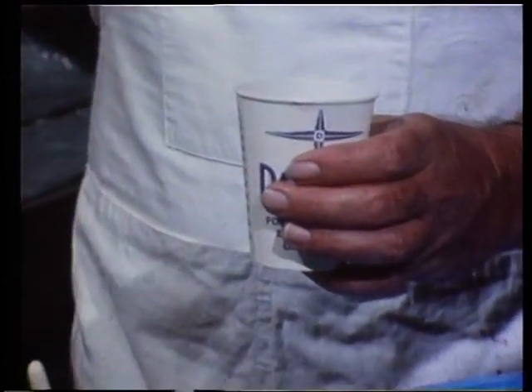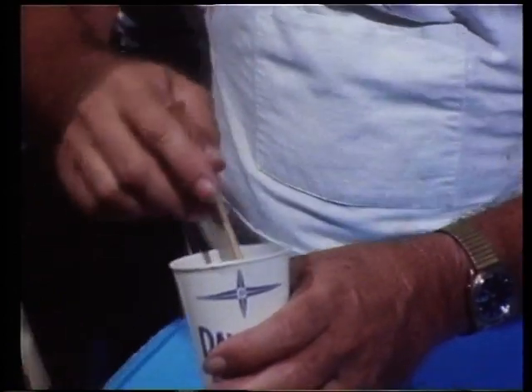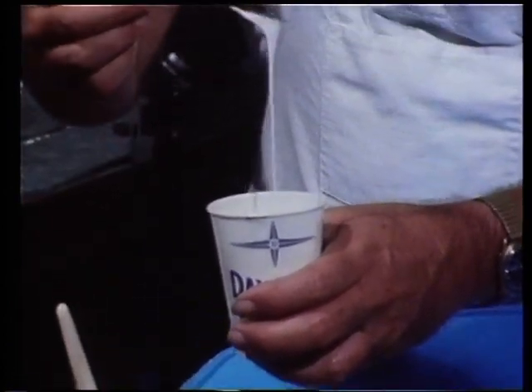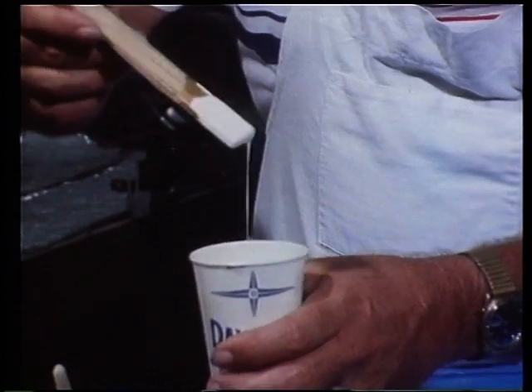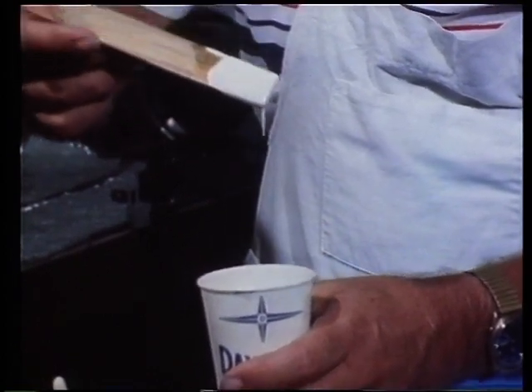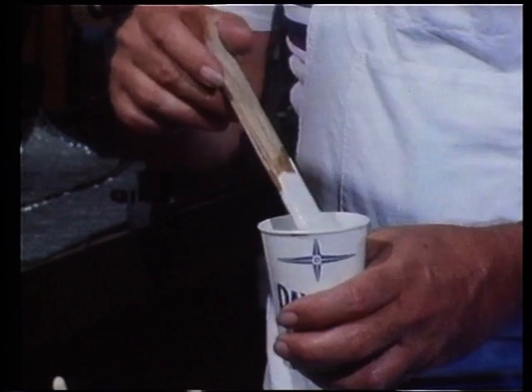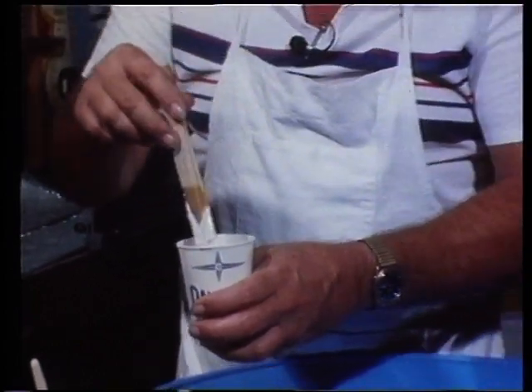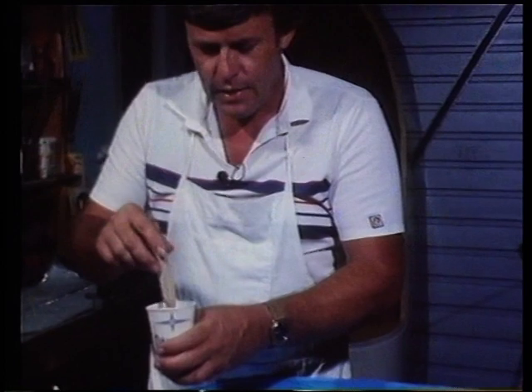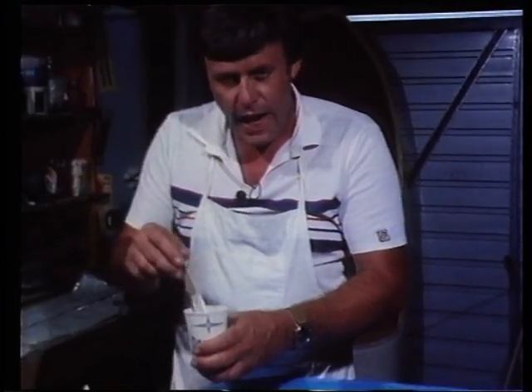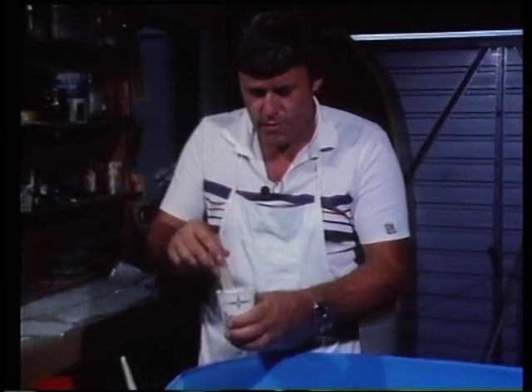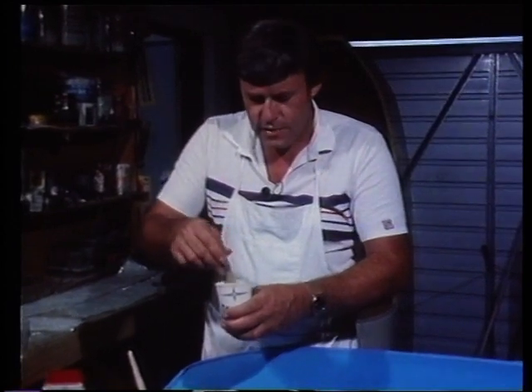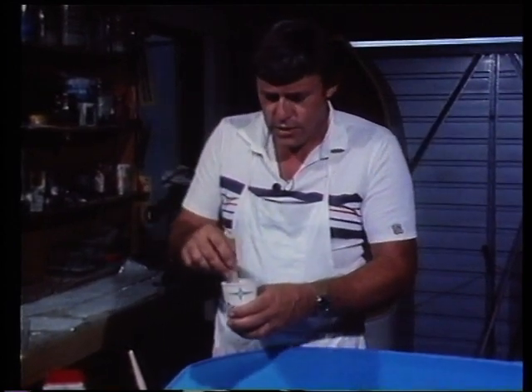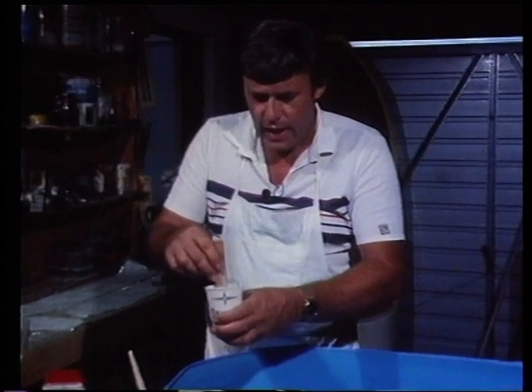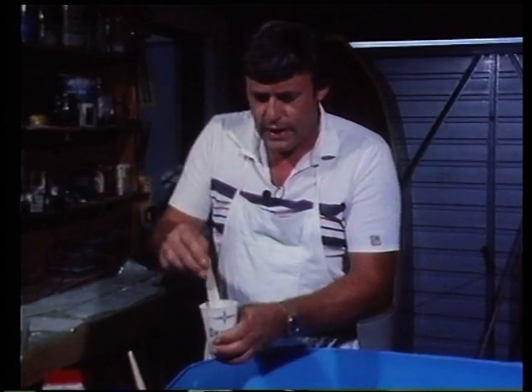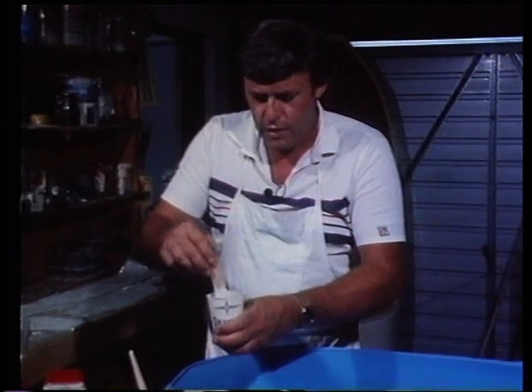Now gel coat has some interesting properties. If I just lift it on the stick there, you'll notice that it pours, but with still quite a large volume on the stick, it stops pouring. Now that means that it has a property called thixotropy. That's a great word, but it means the ability of a liquid to hang up on a vertical surface regardless of its viscosity, and you'll see in just a moment why gel coat has to be thixotropic. Now that means that stirring it, just agitating it like that, is not enough to distribute that catalyst evenly through the full volume of gel coat.